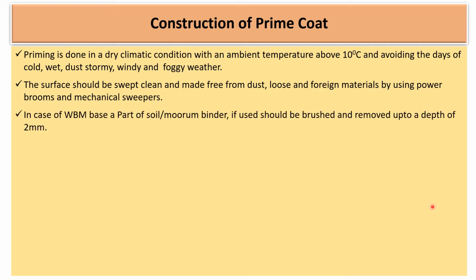Third thing is that if soil or murum has been used as a binder in the case of a WBM road, a depth of about 2 mm should be removed and brushed off from the surface of the base course.